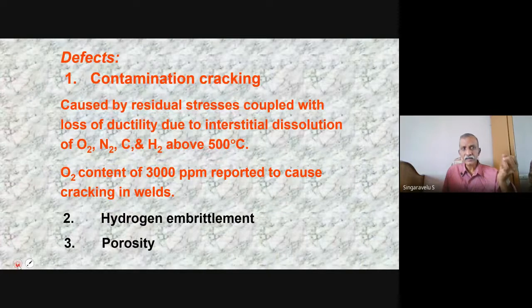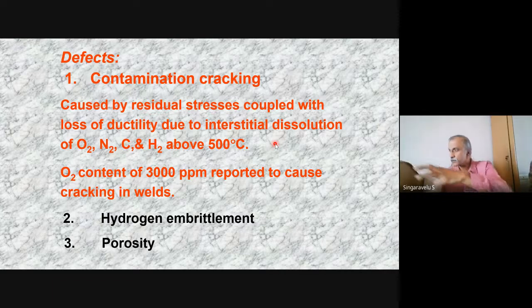Coming to the defect part, contamination cracking is caused by the residual stress coupled with a lack of ductility. Right? The interstitials, as we told, are some of the elements which go into solution in between the titanium atoms, like oxygen, nitrogen, carbon, hydrogen. See, oxygen plays a very important role. Its content of almost about 3000 ppm causes cracking in the weld. Right? Hydrogen embrittlement and resultant porosity also. Right?